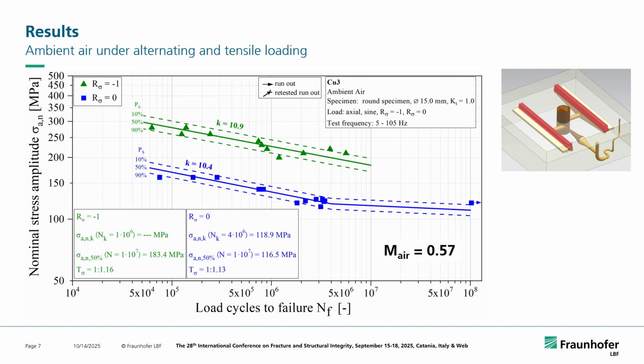Looking at the results, first of all, under ambient air, we made some tests on alternating and tensile loading. We saw until 10 to the power 7 for alternating loading not really a knee point. That was a bit surprising. We saw one for tensile loading. At the end, we stopped at 10 to the power 7 cycles here and assumed, okay, probably this will go on with this 10.9 value for the slope in the medium cycle fatigue range further on to a very high cycle fatigue range. At the end, if we calculate the mean stress sensitivity, we come to something around 0.57 here for this material, taken from those 50 millimeter blocks.